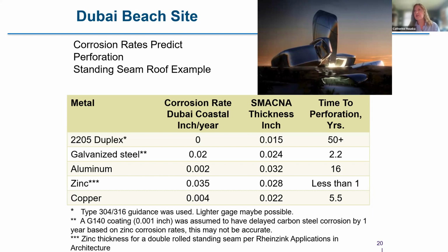I converted it into something that probably means more to most who are working on buildings. I assumed a roof, and I used the thickness right out of the SMACNA architectural sheet metal manual and put in the corrosion rate and calculated the time to perforation. This is based on the average corrosion rate, so perforation could well occur before that. 2205, depending on the finish, did have some very light staining as they extended the testing, but it wasn't measurable. So the time to perforation would be over 50 years.